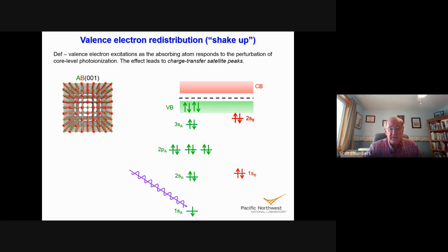But it turns out there's a non-zero probability that, in addition to that, you can have other states of the ion where you get charge transfer. For instance, we could have charge transfer from the green to the red. This is a different final state of the ion than the one I just showed you. Or we could have charge transfer from the red to the green, and that is yet a different final state of the ion. And there are lots of different final states of the ion here, depending on how many of these events have some non-zero probability.